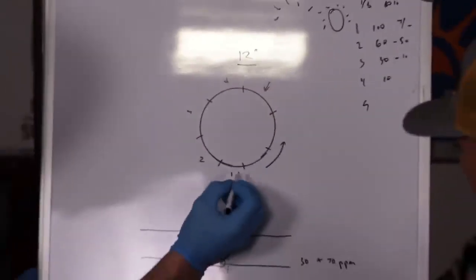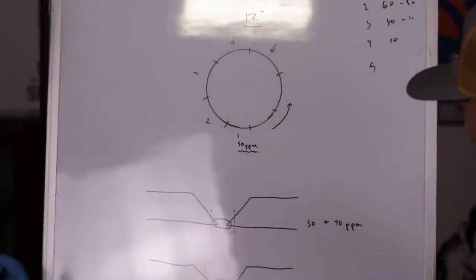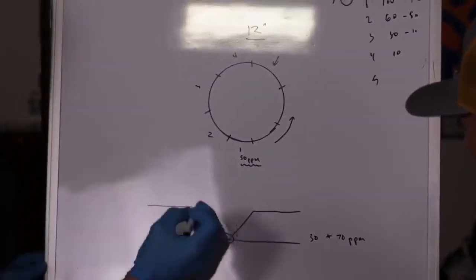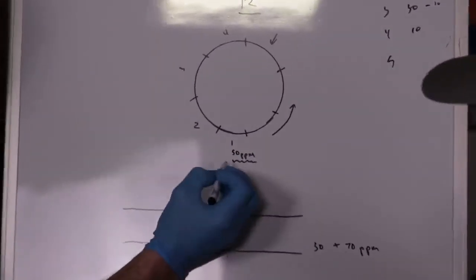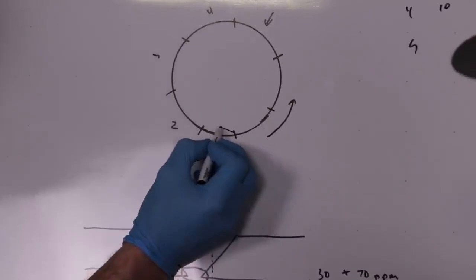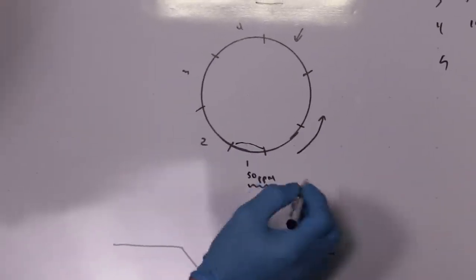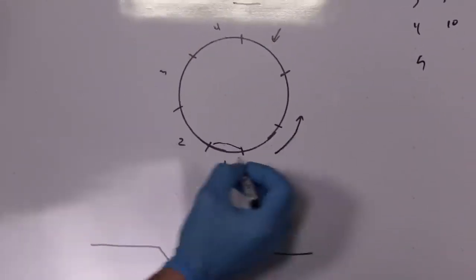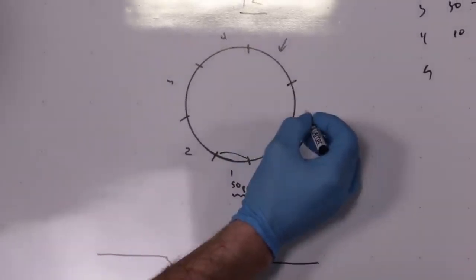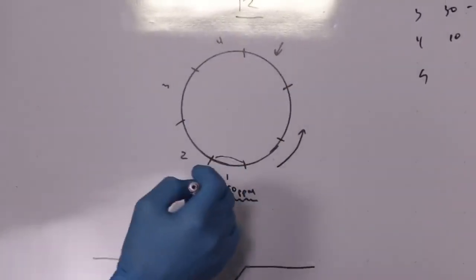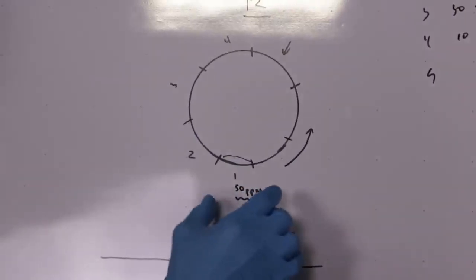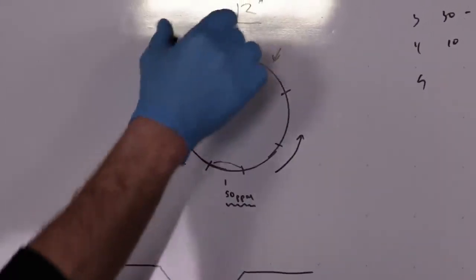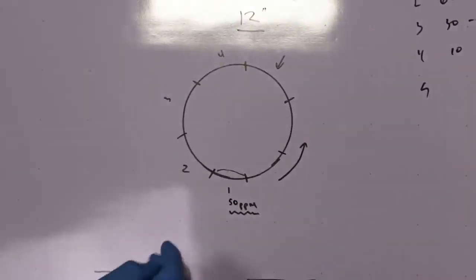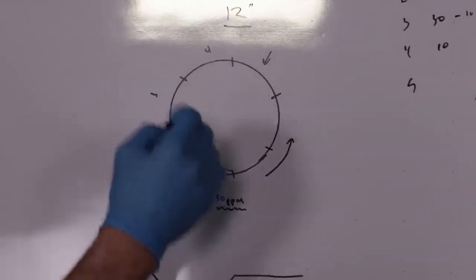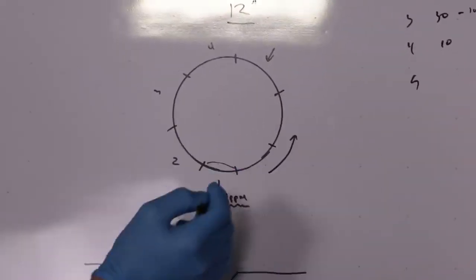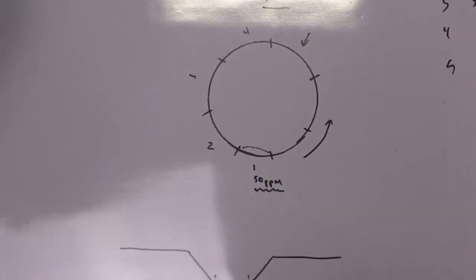So when you start welding, you'll remove a little bit of tape at the bottom, because the bottom is going to be the very worst parts per million of oxygen. Say you get, hypothetically, 50 parts per million. So you're going to weld the bottom, and it depends on where you adjust the heat. Maybe you might weld down here and up here, over here, welding different areas of pipe while allowing previously deposited metal to cool down. You're welding somewhere else, and also the counter pull, and also depending if it's stainless, you might counter the influence and effects of gravity and how the material sinks everything.